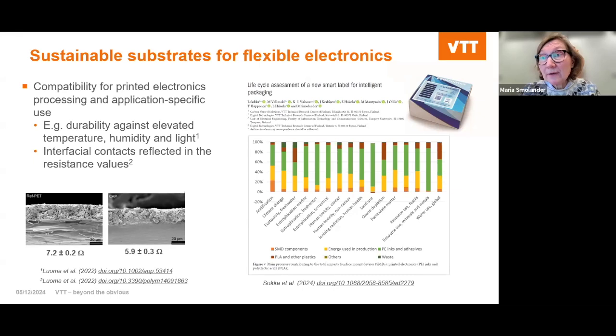But we also looked, for instance, at cellulose acetate propionate. And in the example shown in the picture here, it can be seen that when the conductivity or the resistance of a print pattern was compared between these two substrate materials, the resistance decreased when the material was changed from PET to cellulose acetate propionate. And actually, this is a really nice observation, because it means that we don't necessarily need to compromise on performance when we go from conventional fossil-based material to bio-based materials.